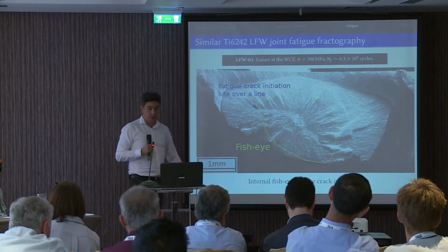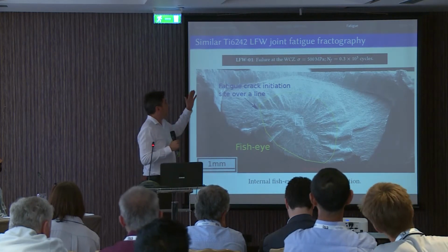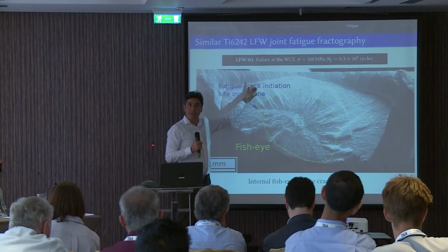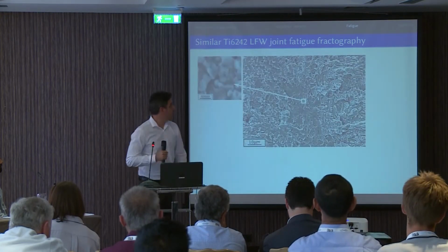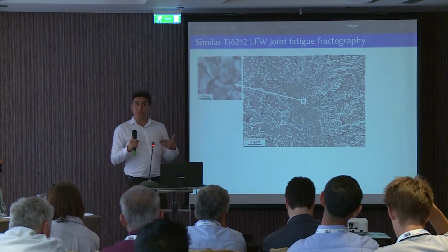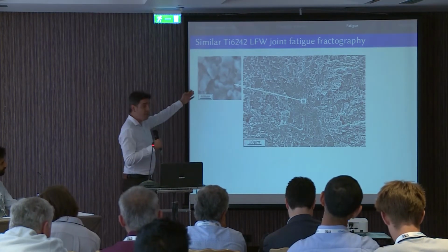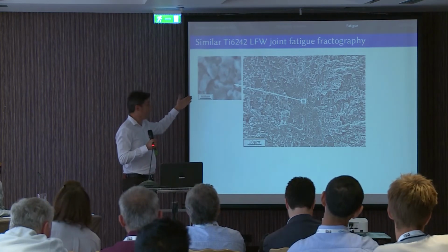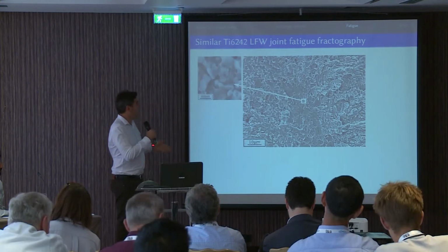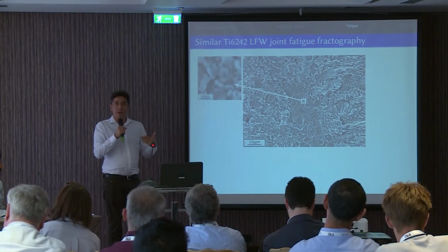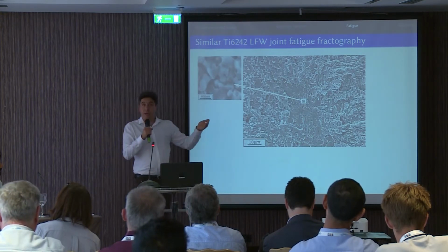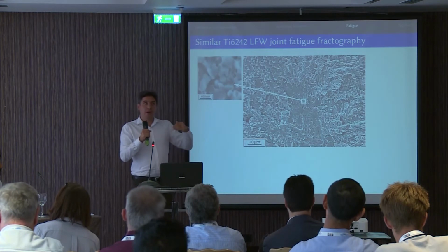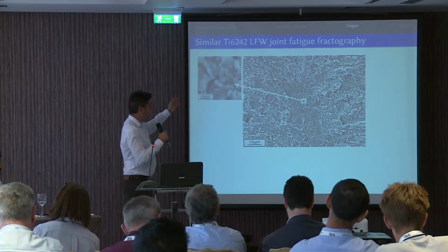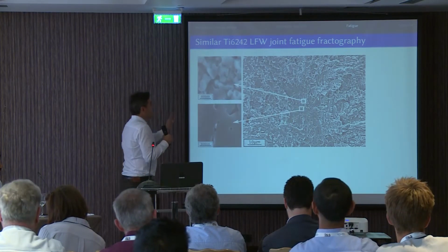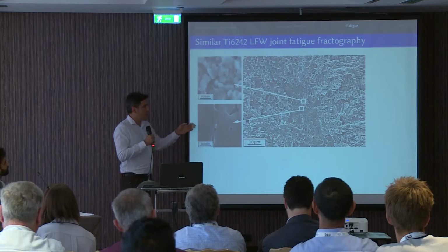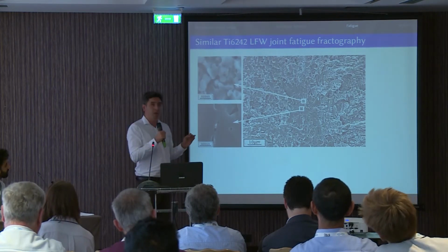So we are going to take a closer look. As a reminder, we're talking about the specimen that broke at the weld center zone. If you remember the morphology of the microstructure at this location, you should be surprised, because these features do not look like the microstructure that we were supposed to find here. These features convey the shape of a dendritic defect. It seems like locally the temperature during linear friction welding overreached the melting point, and so we have the dendritic defect. In the surroundings of these defects, we have facets that suggest a local brittle fracture.